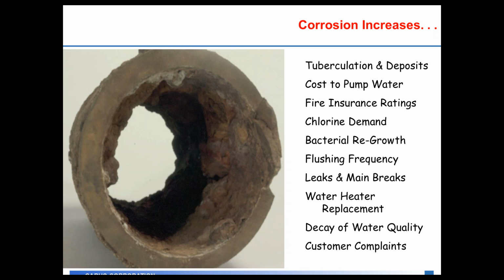One of the first things you do when you have customer complaints is flush the water to flush the bad water out of the system. As scale and tuberculation builds up in the system, you may have to flush different parts of the system more and more times, and every gallon of water that you flush through the fire hydrant is a gallon of water that you've paid to treat at the water treatment plant but aren't recouping any costs as you flush it to waste to try to clear up the water quality issues in the system. Overall, flushing frequency can then lead to leaks and main breaks. As that pipe wall is impacted, the pipe can break and now you have a leak or main break and are losing water to the ground itself.